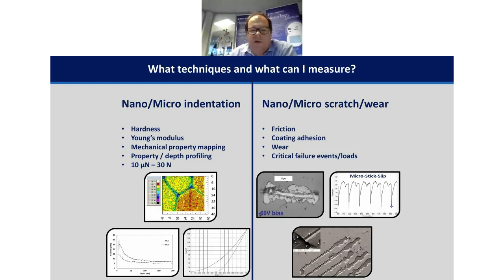We can look at critical failure events and the loads at which they occur. That's quite an important thing along the development path, because two nominally similar coatings, if deposited under different conditions, can actually undergo very different failure mechanisms to each other. We can start to understand what's controlling failure and causing failure through scratch testing.